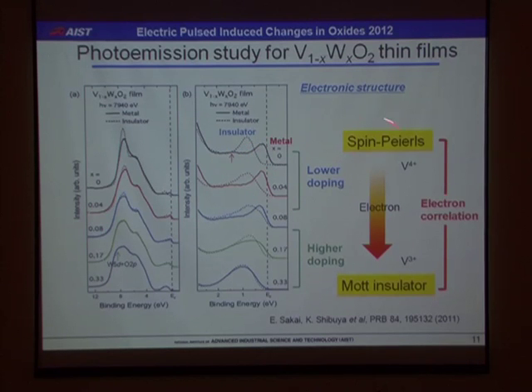This is a typical behavior of a spin-Peierls insulator, and that remains dominant in the lower doping region. And in the higher doping region, Mott behavior was seen, namely the spectral weight change from coherent peak to incoherent peak was observed. So here electron correlation became dominant in the whole concentration region, but the spin singlet instability is weakened with electron doping.